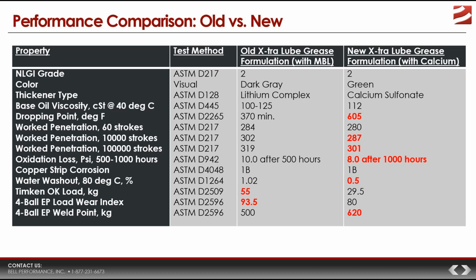So comparing the old and the new X-tra Lube Grease, what you see is that the new grease does have a higher weld point. That's good. The old X-tra Lube Grease actually has a higher load wear index, 93.5 versus 80. Now, at that point, you're like, well, the old grease is better. And since we just explained the significance of the load wear index, we'd say, yeah, the old grease was really good.